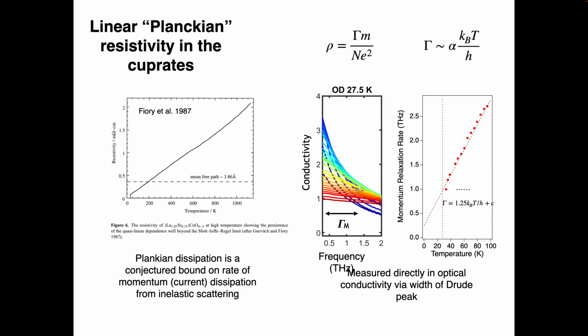There's no Boltzmann perspective. It's not because it's a Fermi liquid, blah, blah, blah. No, this is just the definition of conductivity that comes from what we understood as the spectral response, and particularly that memory function approach. Right? So if I take this quantity here, which rolls off in this particular fashion with frequency, and I inverse Fourier transform to the time domain, as was asked yesterday, I will have a time dependence which reflects this. Okay? And then you can pull out that rate as a function of temperature. And no assumptions. The fact that it's kBT divided by Planck's constant times a number of order 1, this is what's referred to as Planckian dissipation. And it's kind of a notable result. If there are questions, people should just let me know.